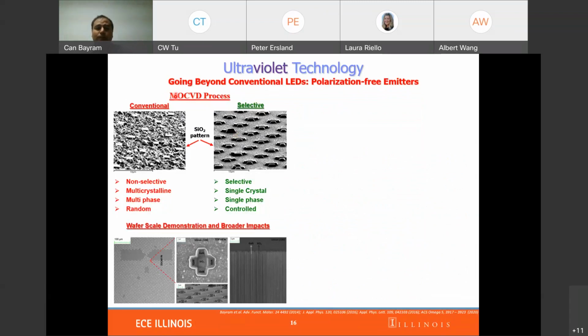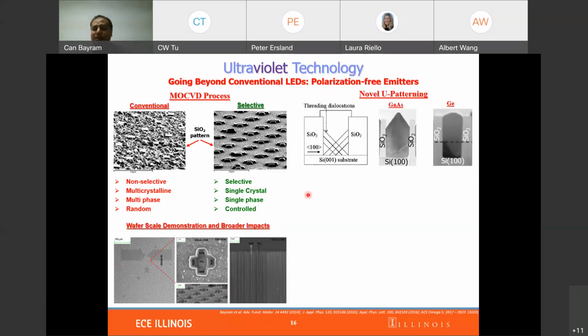So if we try to grow gallium nitride on conventional silicon 100, this is how it looks. Basically, it's a non-selective process, multicrystalline, random, and multiphase. Now we have developed a process where we can selectively nucleate these structures, have single crystal, single phase, and controlled. And we demonstrate this over large areas. Now what does this mean? This means that we can use the selective nature in some sort of an aspect ratio patterning structure.